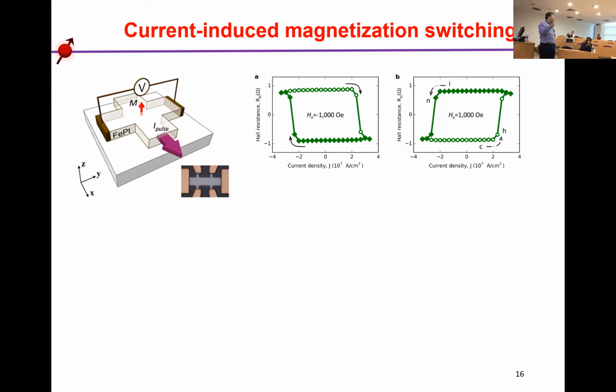When we change the magnetic field direction, we can see the magnetization switching polarity has changed. This phenomenon is similar to the SOT in bilayer structures. Therefore, we think this SOT, which we call the bulk-like SOT, is generated in these materials.